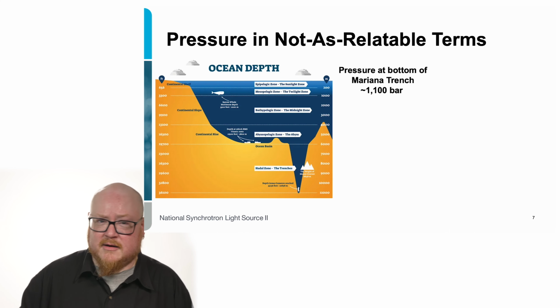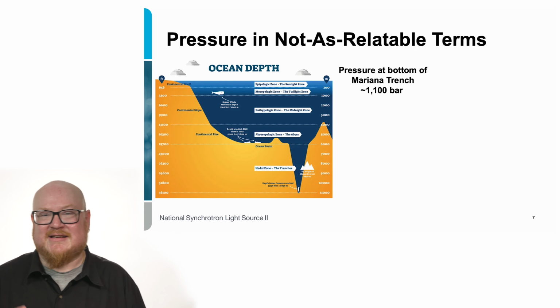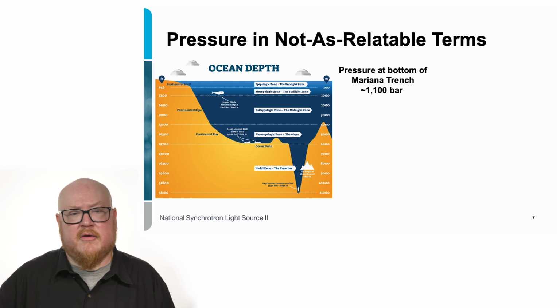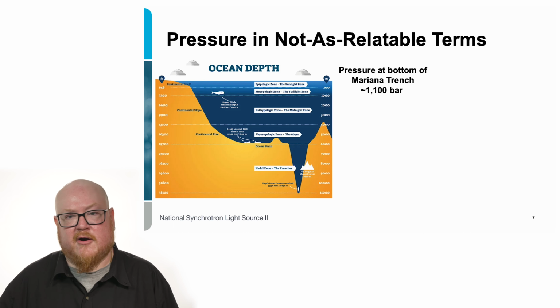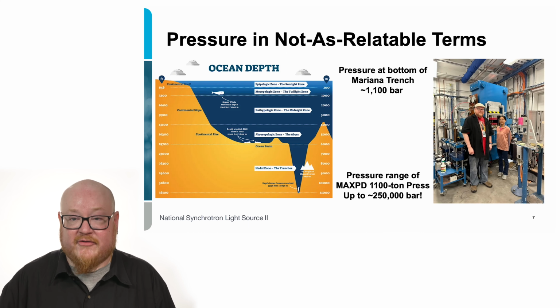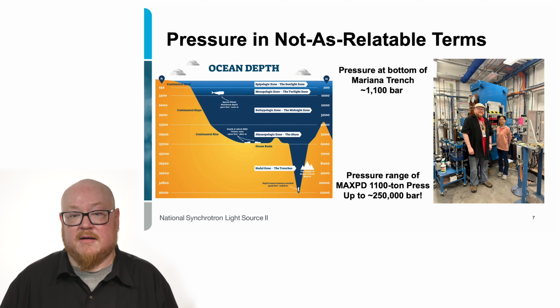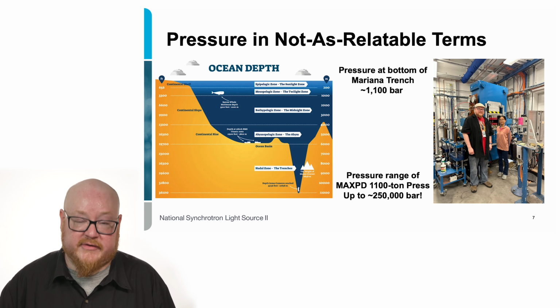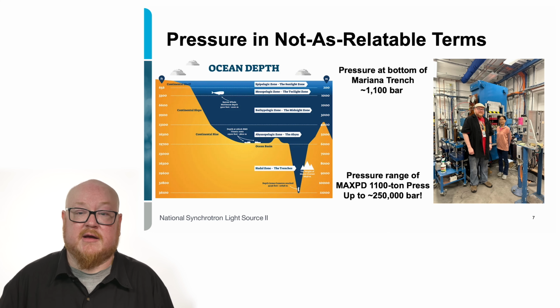Now I'm going to move ahead a little bit further and talk about pressure in not quite as relatable terms. So if we go as deep as we can on the Earth, to the deepest part of the ocean in the Mariana Trench, that's about 1,100 bars, so 1,100 times atmospheric pressure. The press that we have at the XPD beamline is able to achieve pressures that are about 250,000 times atmospheric pressure. So there's a very big range of conditions that we can cover.